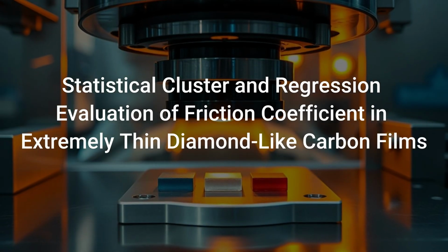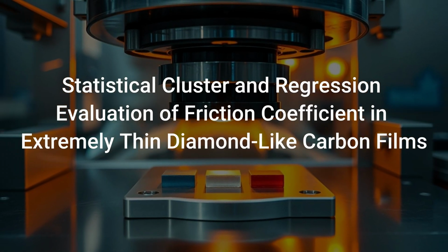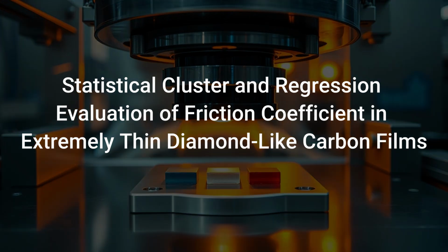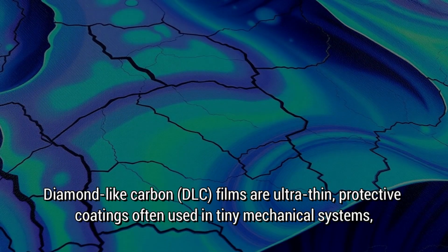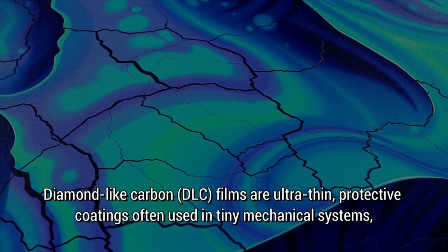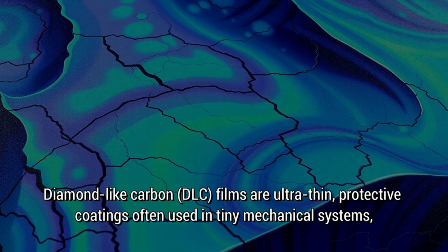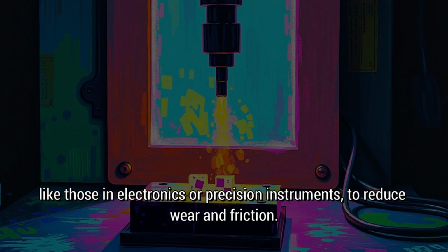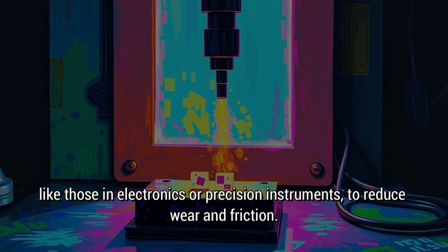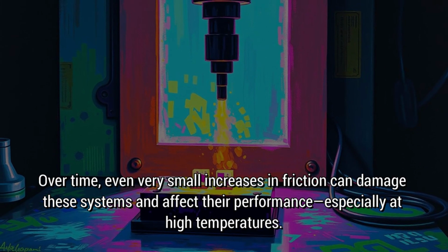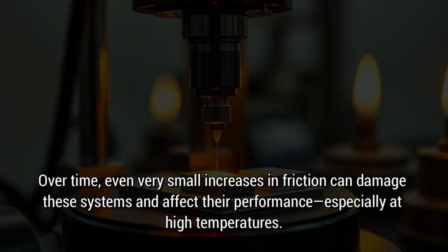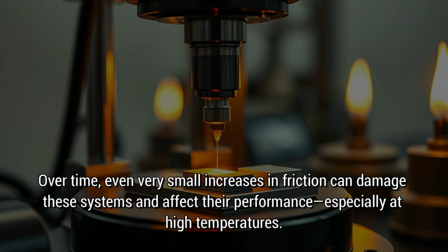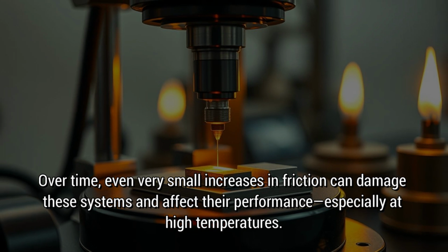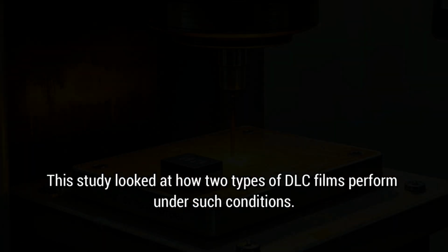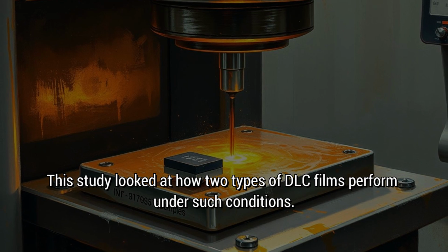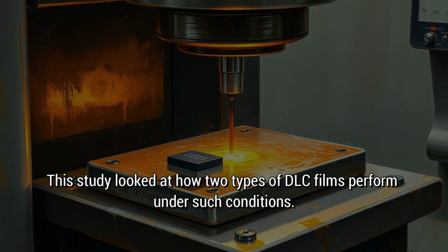Statistical cluster and regression evaluation of friction coefficient in extremely thin diamond-like carbon films. Diamond-like carbon, DLC, films are ultra-thin, protective coatings often used in tiny mechanical systems, like those in electronics or precision instruments, to reduce wear and friction. Over time, even very small increases in friction can damage these systems and affect their performance, especially at high temperatures. This study looked at how two types of DLC films perform under such conditions.